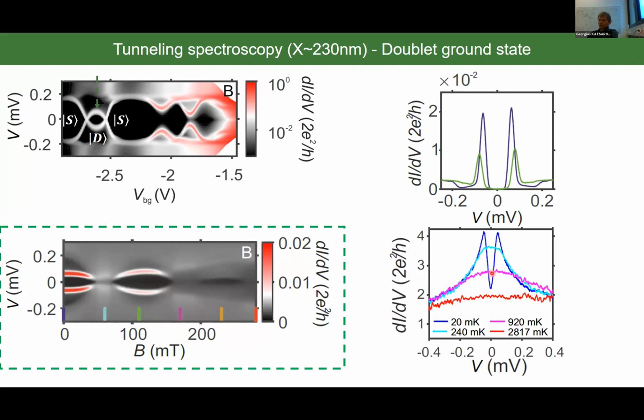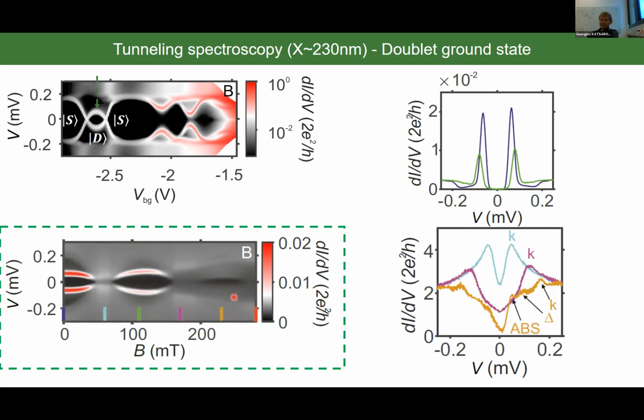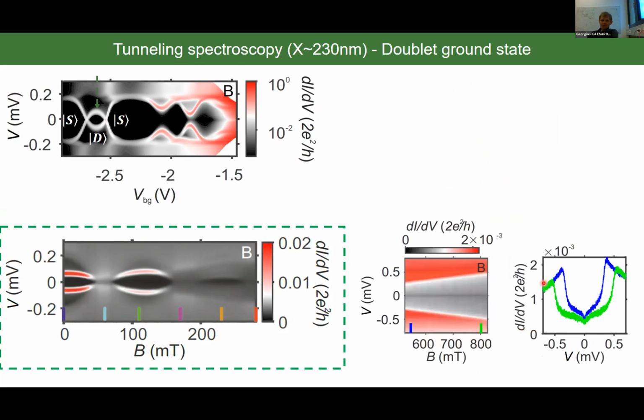And in order to confirm that, we did a temperature dependent measurement. The Kondo peak disappears a bit below 3 Kelvin. So it is interesting to note that in the 0th lobe and in the first lobe, where we have a hard gap, we can see just Andreev bound states. When we kill superconductivity, we see just the Kondo effect. But in the second lobe, where we have a soft gap, we can actually distinguish both Andreev bound states and Kondo. We now use the Kondo effect in order to extract the g factor of our nanowire.